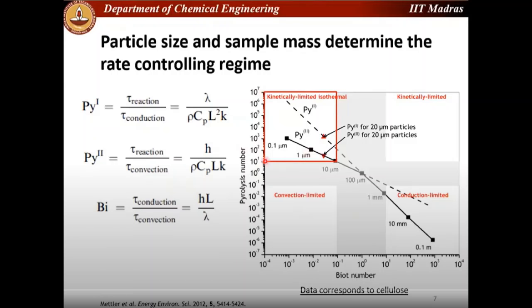Whatever the material going to be pyrolyzed, small mass and small particle size samples are in favor of kinetically limited isothermal regime at which reaction is the slowest step that determines the typical product distribution. Whereas bigger mass and particles are conduction or heat transfer limited, there is going to be gradient within the sample which results in different product distribution. Therefore, small mass and small size are preferred in analytical pyrolysis studies.